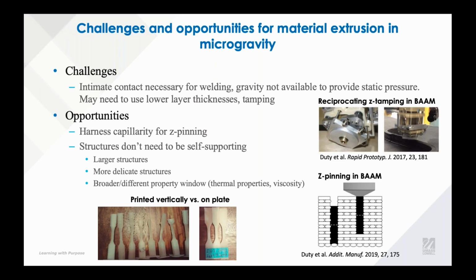So thinking about sort of challenges and opportunities for material extrusion in microgravity, one of the big things to think about is that on Earth, under Earth's gravity, we almost always have that intimate contact that's necessary for welding, just because we're extruding the polymer and then it drops because of gravity. And so we may need to change some of the design in terms of using the extruder tip to actually press down and provide that pressure. Another thing to consider, which is used in BAAM in a lot of cases, is reciprocating sort of Z-tamping in order to provide that pressure and ensure that intimate contact occurs.